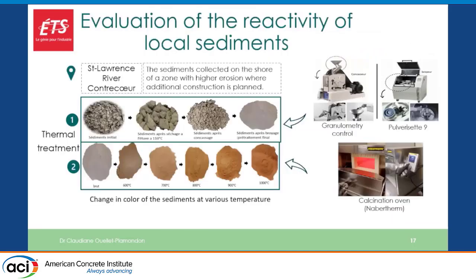And the other line of work that we're doing is to evaluate the reactivity of the local sediment. So we collected sediment on the shore where there's planned development. So that's also in a zone with high erosion. And then what we are doing is a set of reactivity tests where we look at the raw material and then we calcine it from 600 to 1000 degrees Celsius, and we did the reactivity test to see, do we need to calcine it, or is the raw material good enough? How much can we replace cement with it?